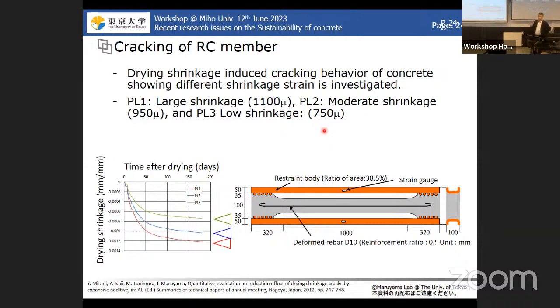So now, of course, you know, the aggregate type is very important for concrete quality. And for that purpose, we prepared 3 different concretes whose mixture proportion, volumetric mixture proportion, is completely the same, but only the coarse aggregate type is changed. And one is a very shrinkable one. And in this case, we see the large shrinkage like this. And if we use, for example, the pure sedimentary limestone, in this case, we see very small shrinkage, like 650, 750 micron in this case.